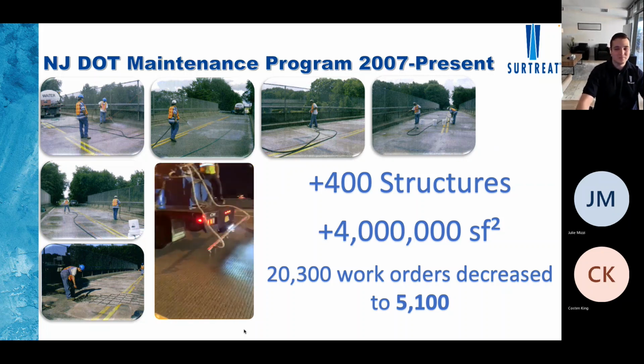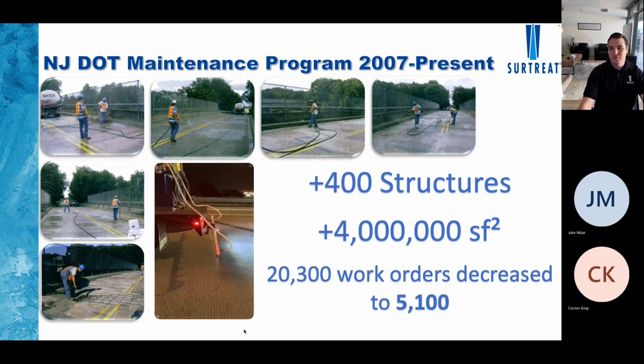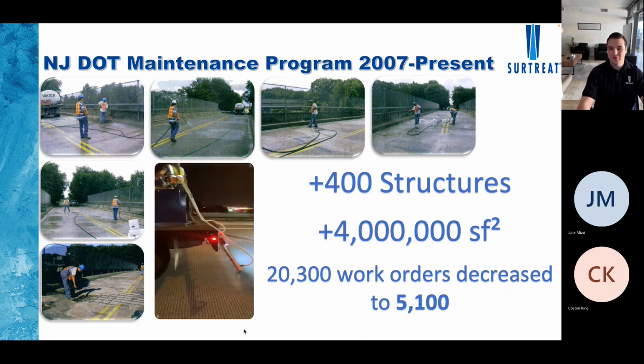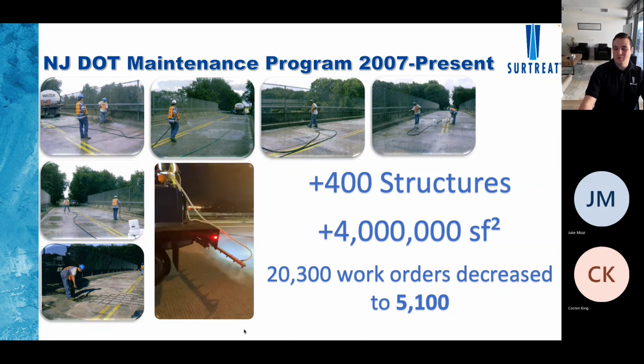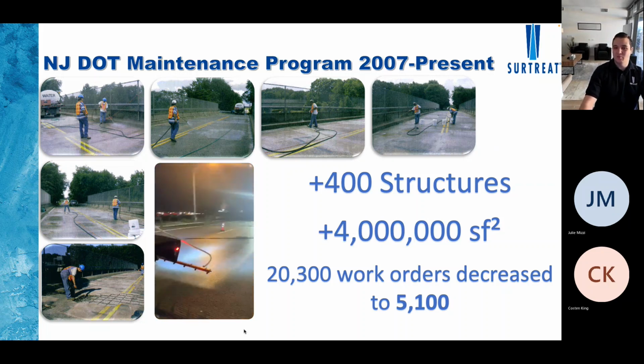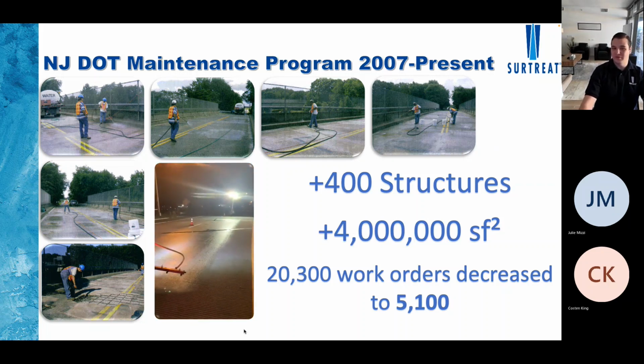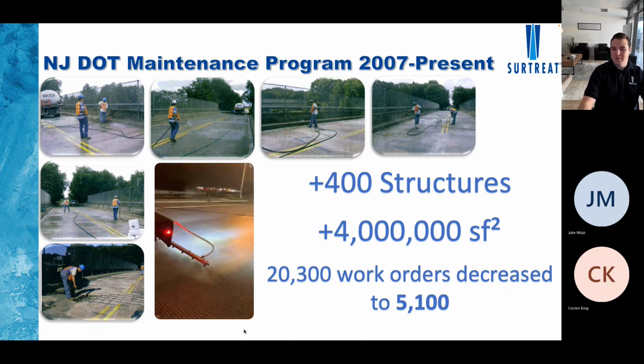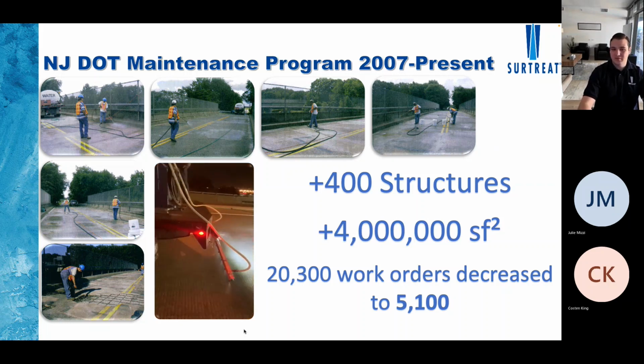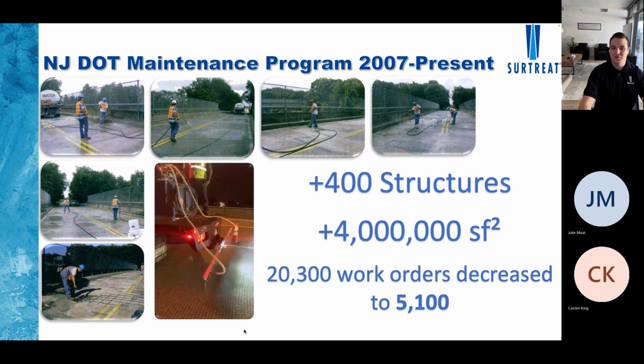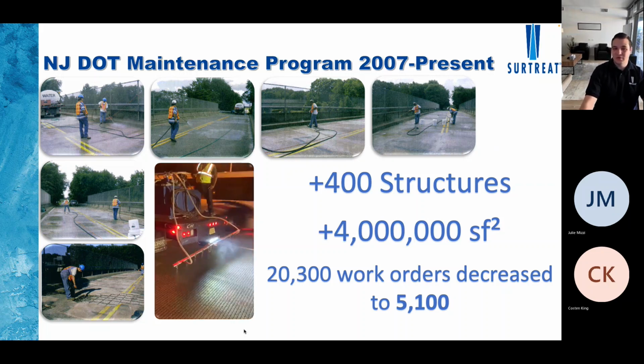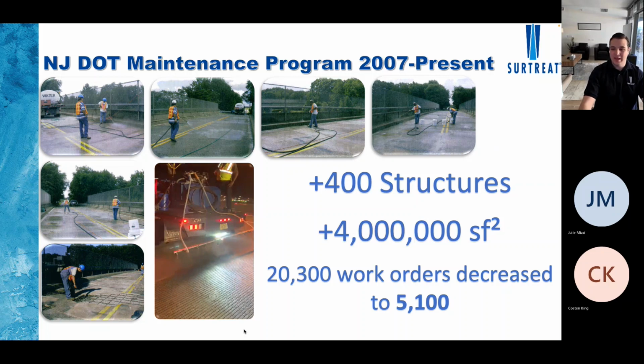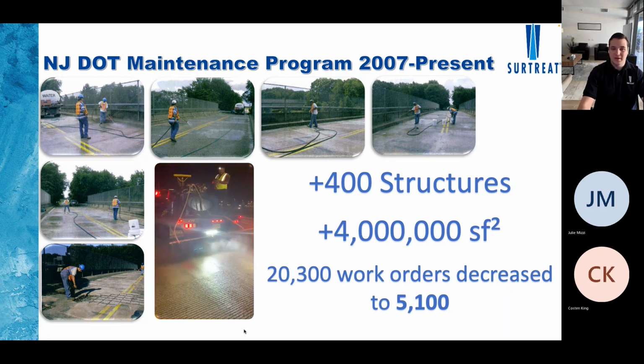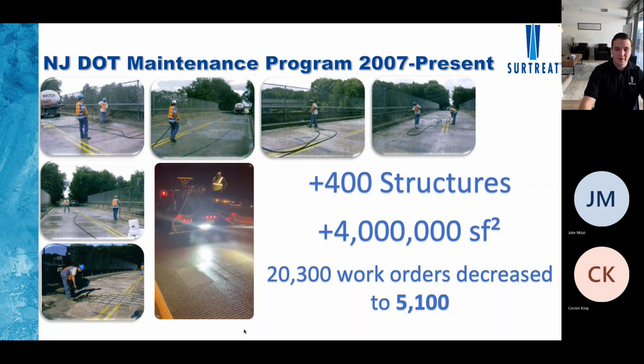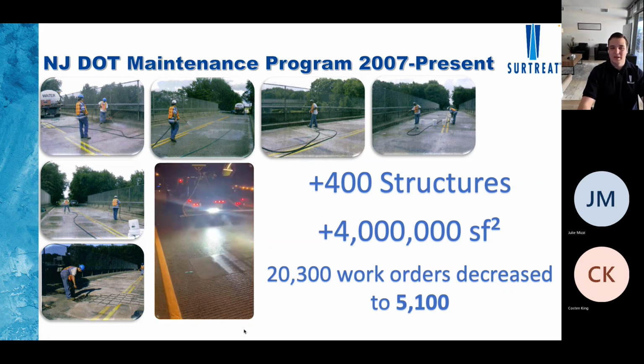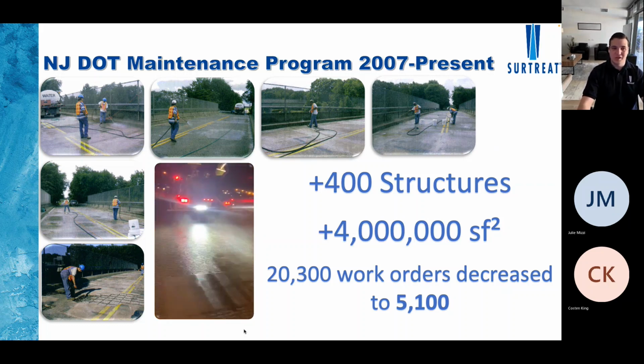So our partnership with New Jersey started in 2003, when Surtreat began a testing program for 4 bridges that were to receive deck treatment. We started with non-destructive core testing before and after Surtreat, and then we sent those results to the University of Florida, where they analyzed the results before and after. We left control areas that were untreated in the deck, just to be able to measure the change.